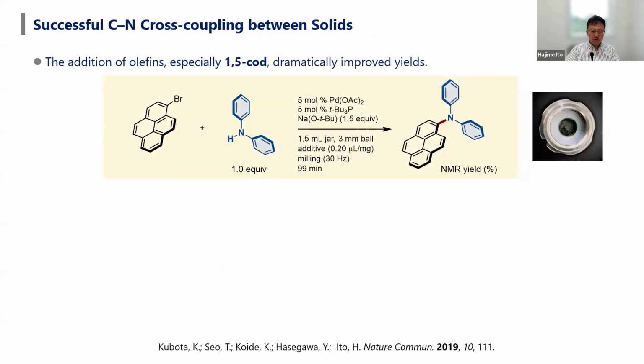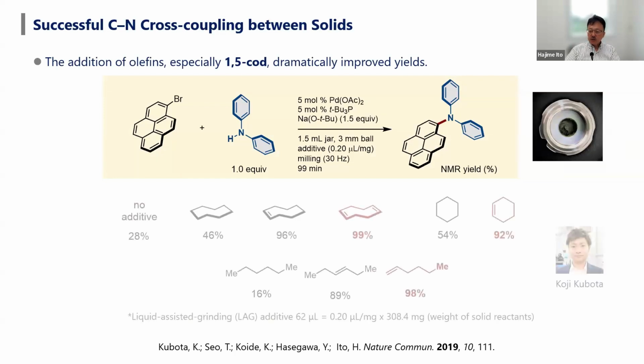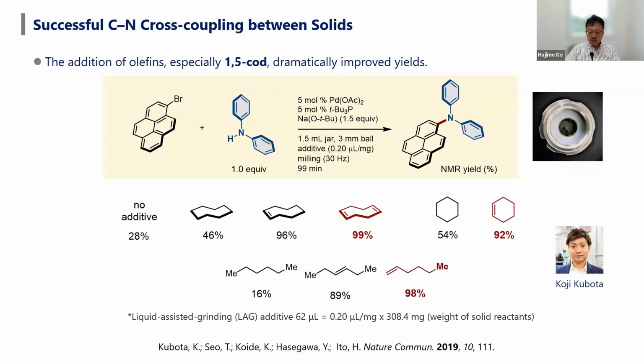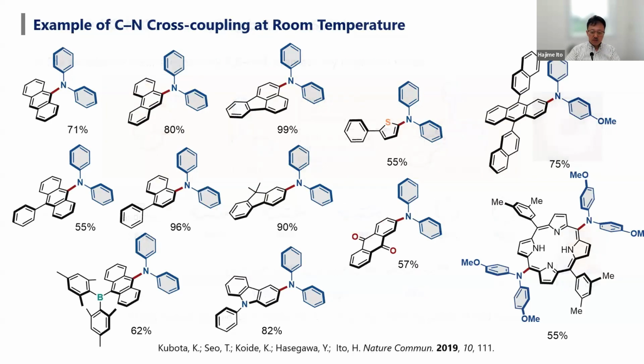The starting point of our study was to find good reaction conditions or additives to improve this reactivity. Dr. Koji Kubota is a very capable person, and he quickly found that addition of 1,5-COD improved this reaction very much by stabilizing the palladium catalytic species. These are examples of cross-coupling using this palladium catalyst including 1,5-COD, and we found that this reaction condition is very general.